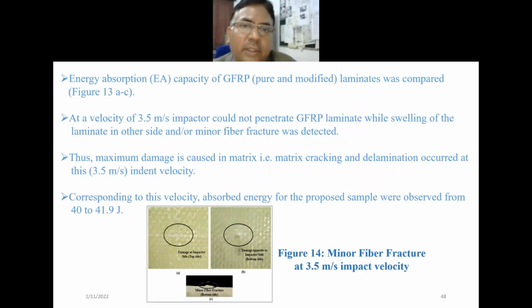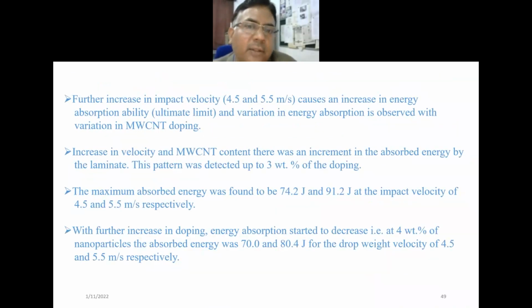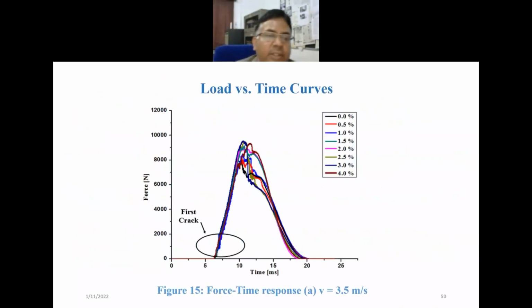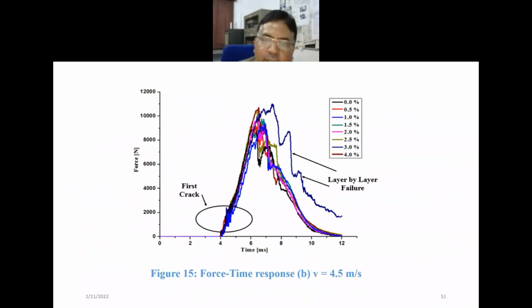So the energy absorption capacity of GFRP, pure and modified, is in figure 13 A to C at a velocity of 3.5 meter per second. Maximum damage is caused at 3.5 meter per second impact velocity. Corresponding to this velocity, the absorbed energy of the proposed samples ranged from 40 to 41.9 joules. Okay. So like that, we have tested different weight percentages.